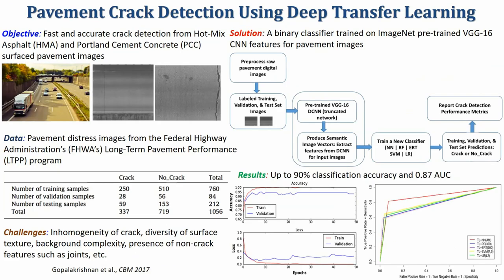And then we have tried to apply these techniques to macro scale images. Those were all microstructure, micro scale images. Here we are looking at pavement images like this. The Federal Highway Administration has a program where it collects these kinds of images, and the goal is to find places or stretches of the roads where there are potholes or cracks and so on, which need more attention before an accident happens. So we took a small subset of the database, which was classified as crack and no crack. This is a labeled data set, and here we're using transfer learning for these models, because this is a comparatively small data set.